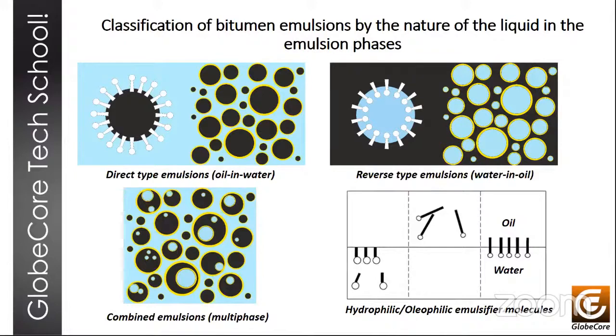We can summarize that direct emulsions are formed when surfactant molecules with a highly hydrated polar group and a moderately developed hydrophobic part are introduced into the system. Inverse emulsions are stabilized by surfactant molecules with a weakly hydrated polar group and a highly developed hydrocarbon part, preferably containing 2 to 3 hydrocarbon chains, as in the case of multivalent metal soaps.